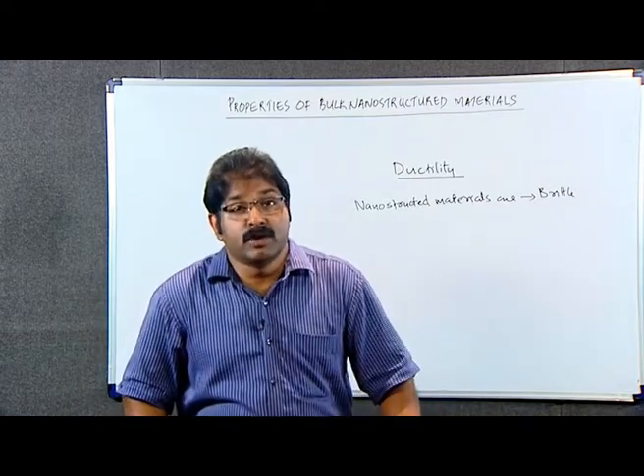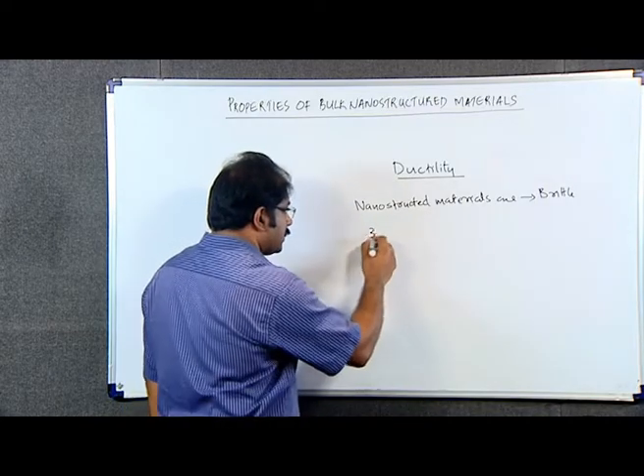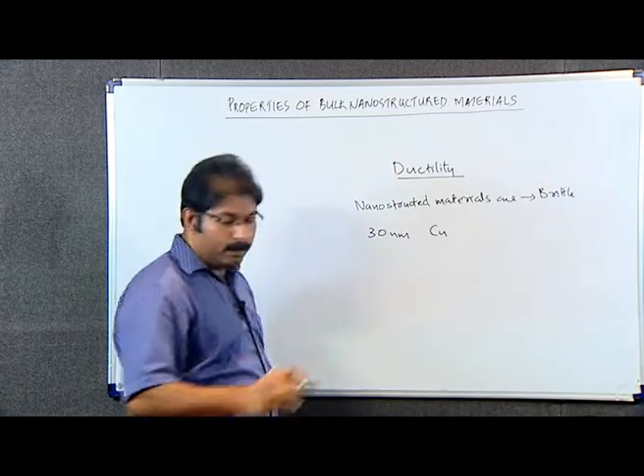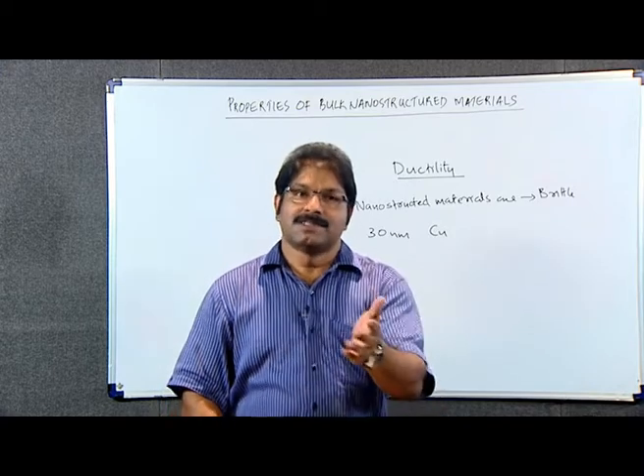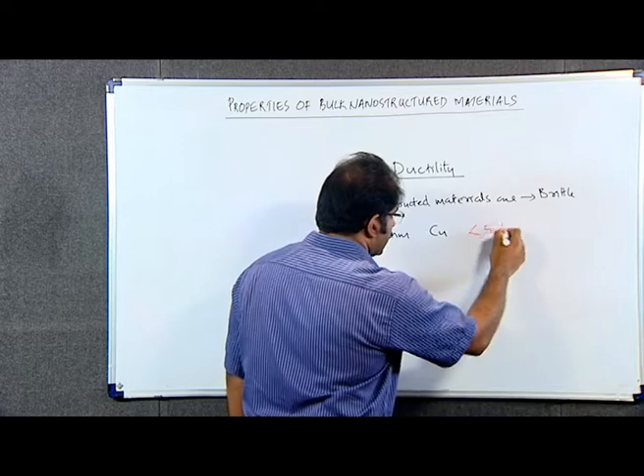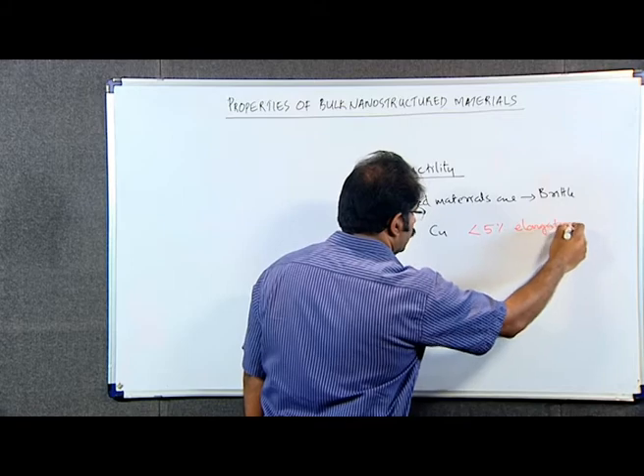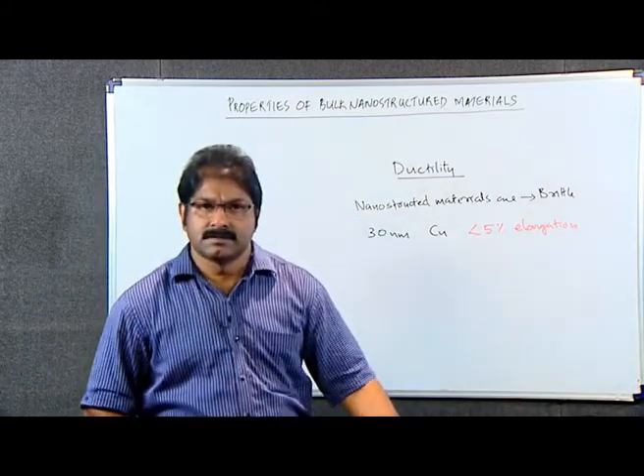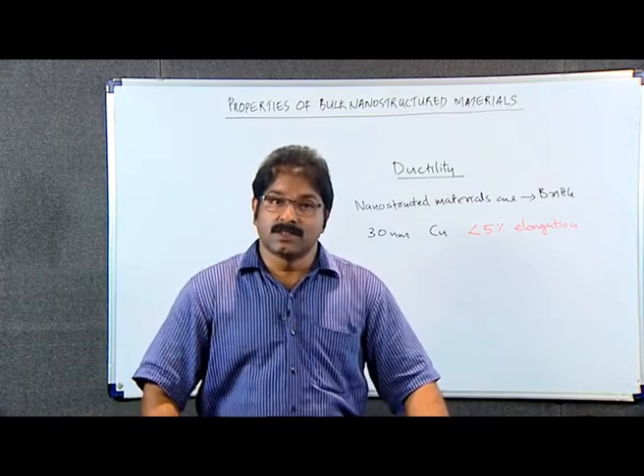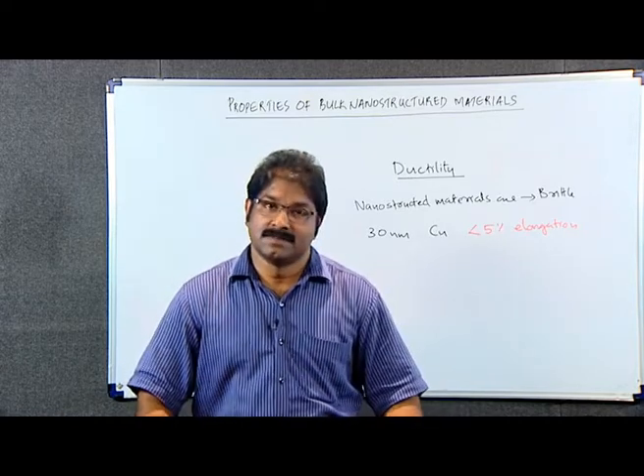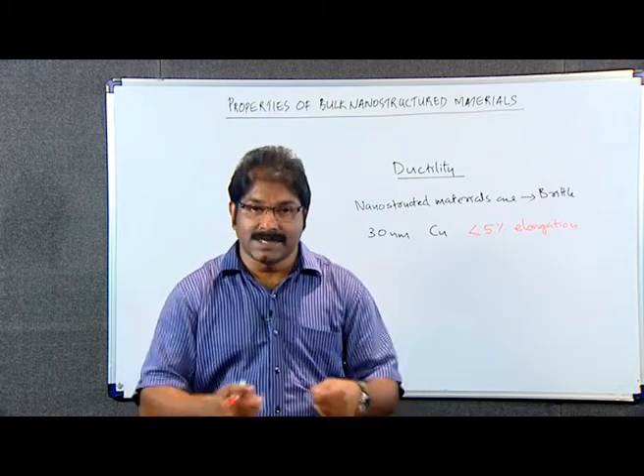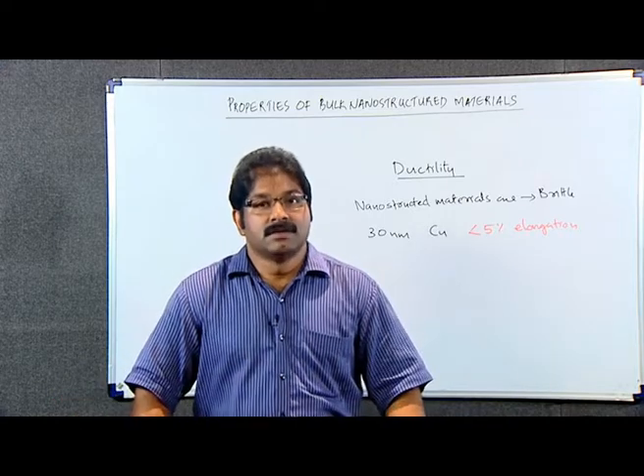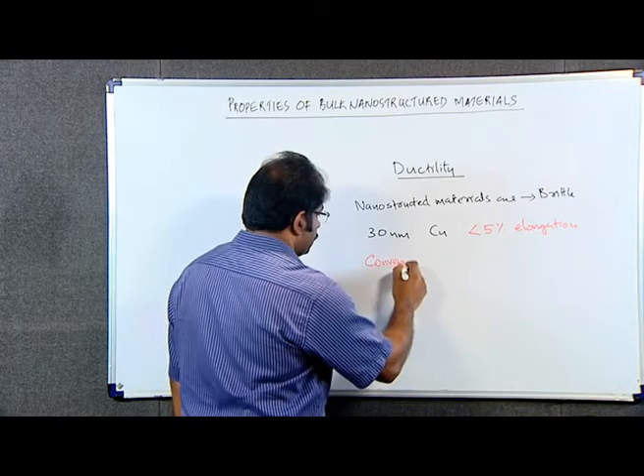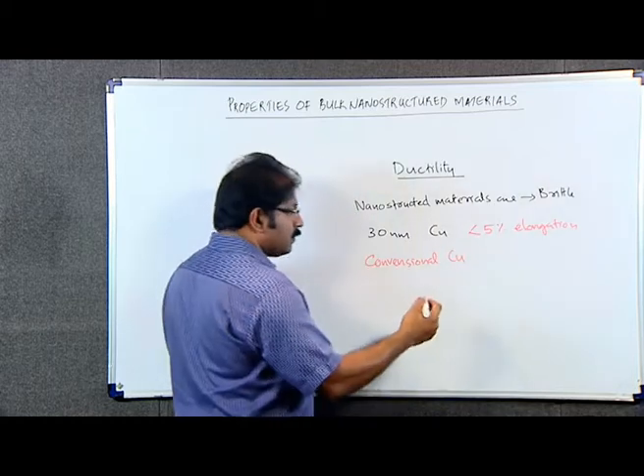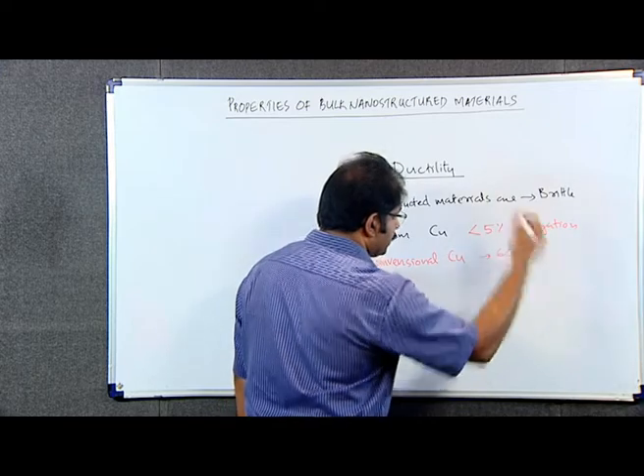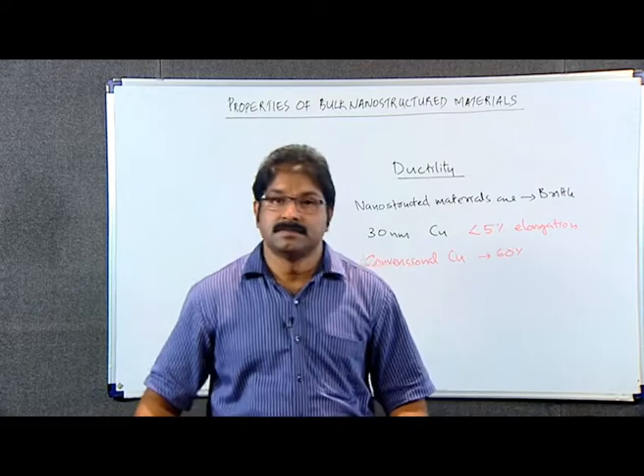For example, 30 nanometer grain sized polycrystalline copper has very less elongation, less than say 5%, which means they have very small ductility. At the same time, a conventional grain size copper shows an elongation up to 60%. That is, conventional grain sized copper could be stretched to about 60% of its original length. So, they are very ductile.